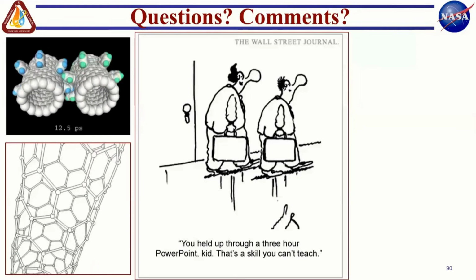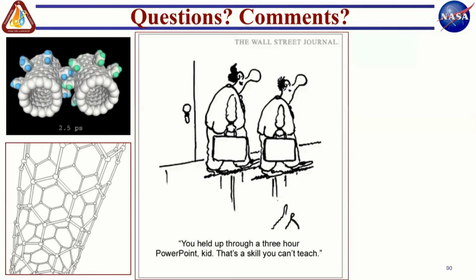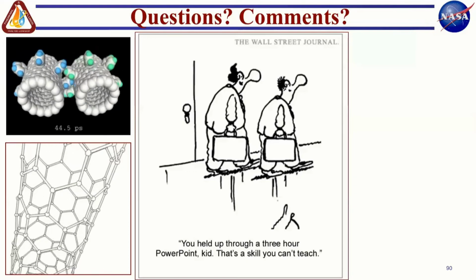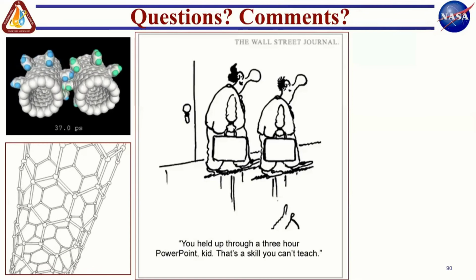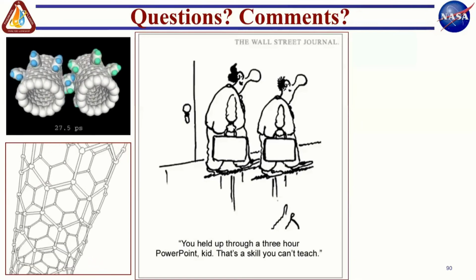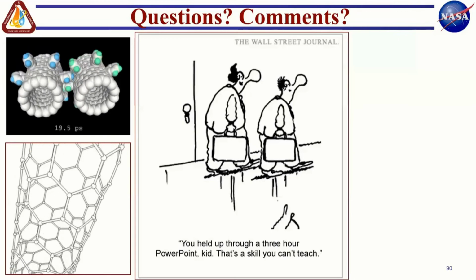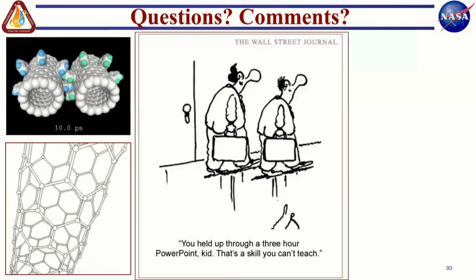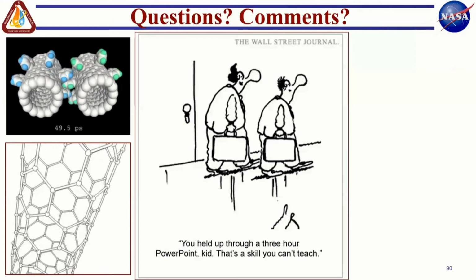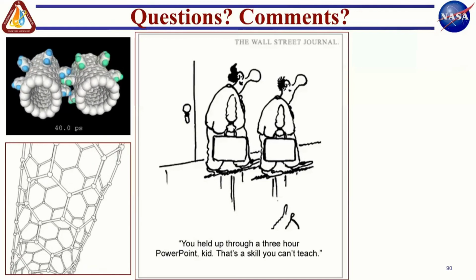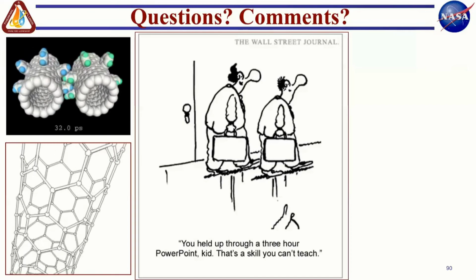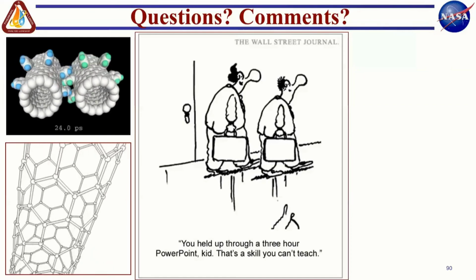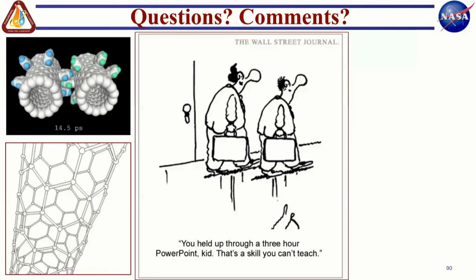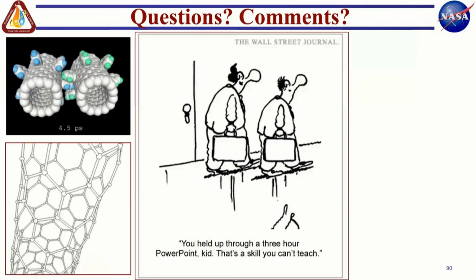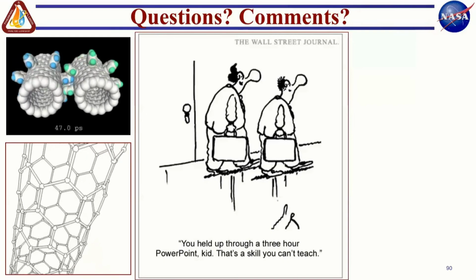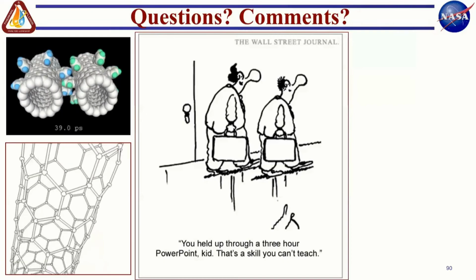And water being a polar fluid, you will get your hydrogen ions and the hydroxyl ions. And of course, your carbon nanotube, depending on how it is manufactured or fabricated, can have an affinity for either hydrogen or hydroxyl ion, depending on whether you have surface oxidized the carbon nanotubes or not. So in other words, depending on the configuration on the surface of the carbon nanotube, you can have a higher concentration of hydrogen ions on the surface compared to in the bulk. So you have created a concentration gradient going from the surface of the carbon nanotube to the